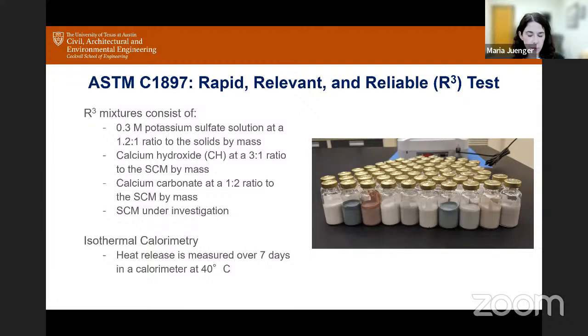And then you have two possible means of analysis, only one of which I'm showing here, which is measuring the heat release using isothermal calorimetry over a 7-day period. You can also measure bound water, curing it at 40 degrees and measuring the bound water using a furnace, which is simpler. And actually the industry prefers to do that. In the labs, we prefer calorimetry. And then the industry, if they don't have a calorimeter, they prefer the bound water method.